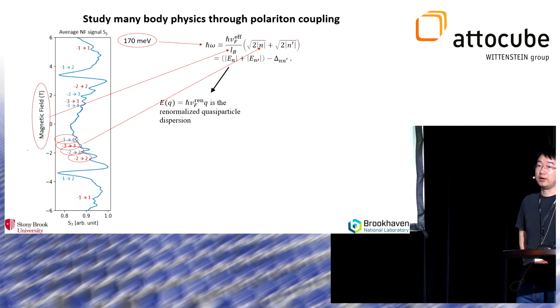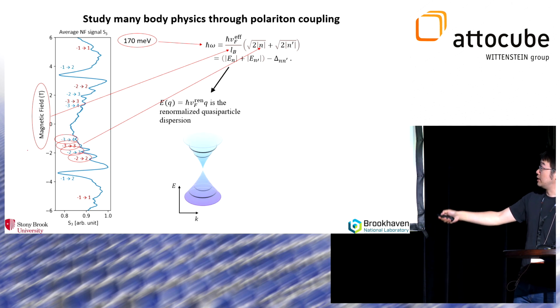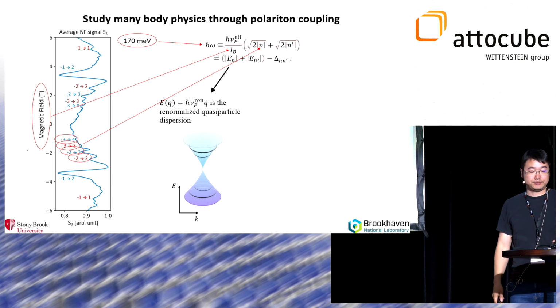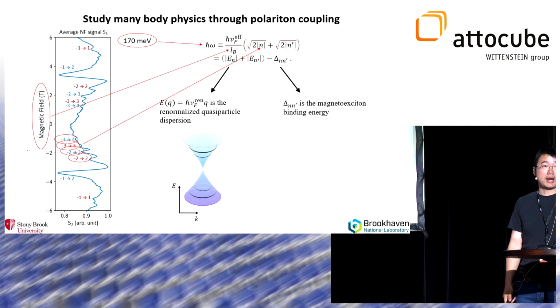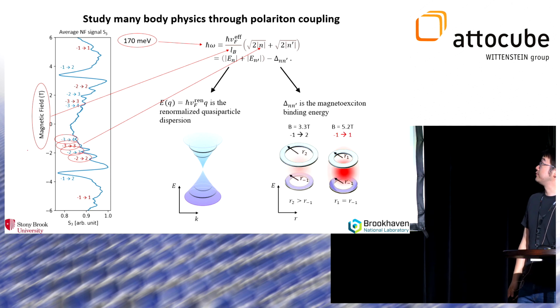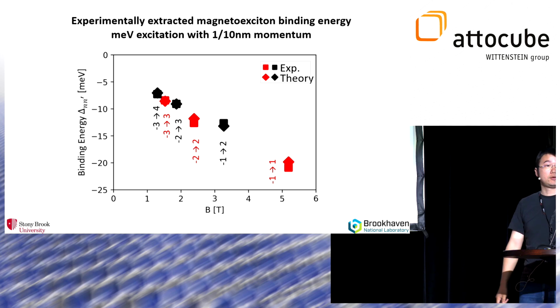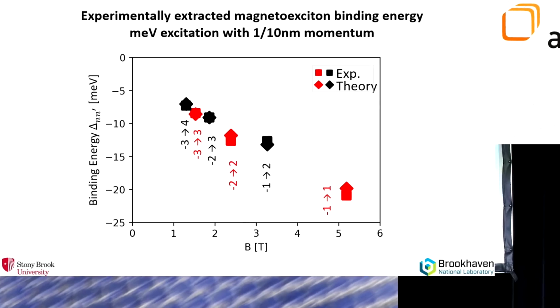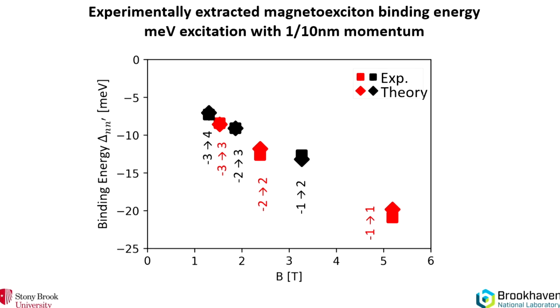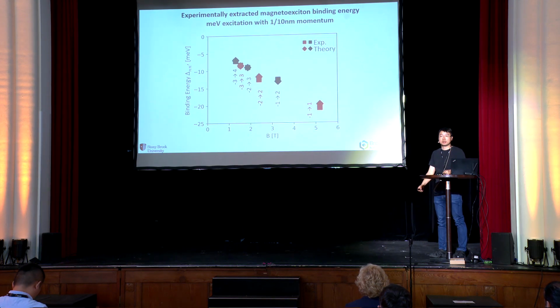One is the Fermi renormalization of the quasi-particle dispersion, so that you have a nonlinear kind of Dirac dispersion. And also you have these so-called magneto-exciton binding energies. Without going into the details, we show that these forbidden transitions, which are the red, actually give you higher exciton binding energies than those allowed transitions. The fact that we can detect the forbidden transitions is because we are now at a non-zero momentum, right? At zero momentum, your -1 to 1, or same-indices, transition is optically forbidden due to the selection rule. But in our case, with near field, I argue that with finite momentum measurements, we have access to all these modes, including the so-called allowed transitions and the forbidden transitions.